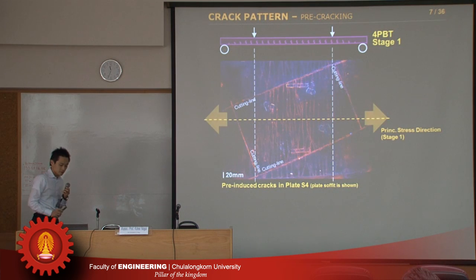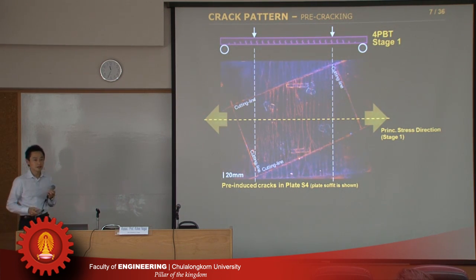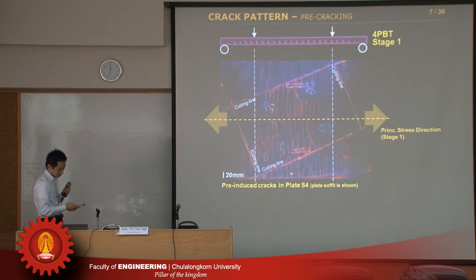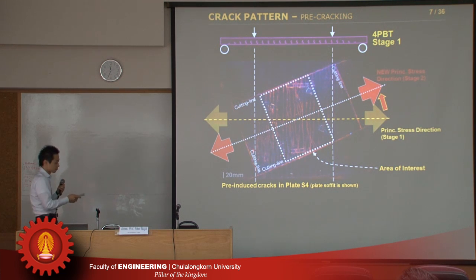So let's look at the cracking pattern. So we use some special powder and give some black light in a very dark room, then we can check the cracking after the test. So this is the initial loading result. This is the main plate, and we give just a bending load, and we have the multiple cracking. This is a feature of the HPLCC that shows a good ductility. And after that, yes, in the test, we cut the plate like this.